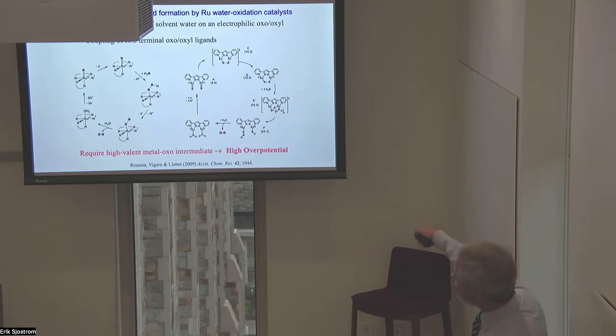There are some ruthenium complexes that have side-by-side oxos, like this one, and they can form an internal oxo-oxo coupling reaction. And now both of the oxygens are labeled, and that's because they both came from the complex and none from the solvent, even though the solvent has a different isotope label. It's not incorporated into the oxygen. So these are two, I would say, classical mechanisms for water oxidation: the so-called water nucleophilic attack mechanism and the oxo-oxo coupling mechanism.